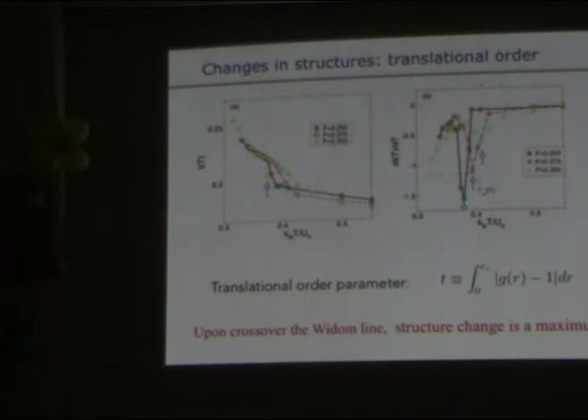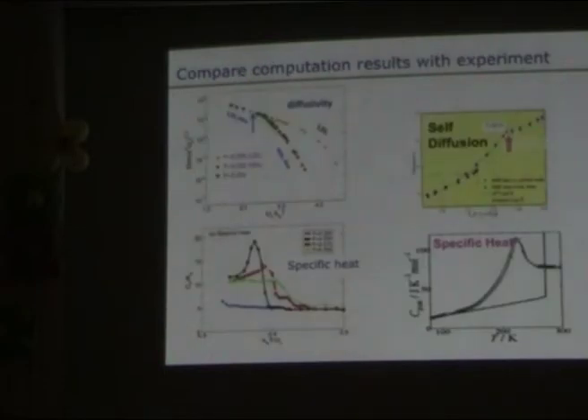So there was some change in the one phase region, and to see clearly, this is the derivative for the translational order. Similar to the orientational order, as you move closer and closer to the critical point, this response function becomes sharper and sharper. And until the end, if you're extremely close to the critical point, this becomes divergent. So therefore, you can see the structure, dynamics, and also thermodynamics. All of these things give you the indication that you can use them to trace the critical point in your system. Now let's compare all our results with experiment.